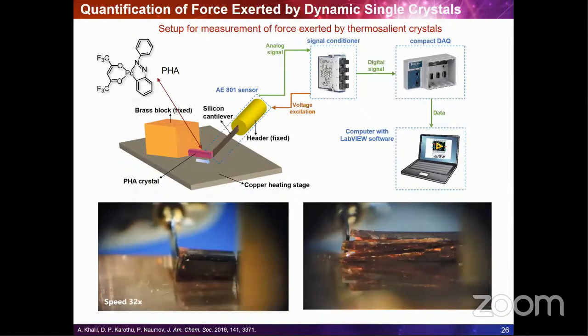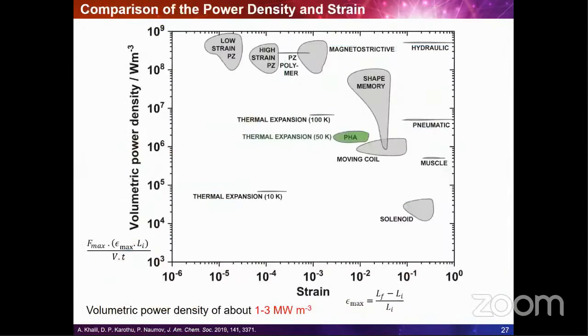Further on, we can actually make plots which represent this kind of performance and compare it more directly with other materials. So, for example, in this plot, you can see the values from the previous experiment that I mentioned, which are co-plotted against respective values for other actuators. You can see that the volumetric power density of the crystals exceeds the values for some common materials, such as moving coils and some shape memory actuators with comparable strain values. Also, in comparison with the thermal expansion actuators, the strains that can be reached with this small crystal are an order of magnitude higher without a significant toll on the volume power density.